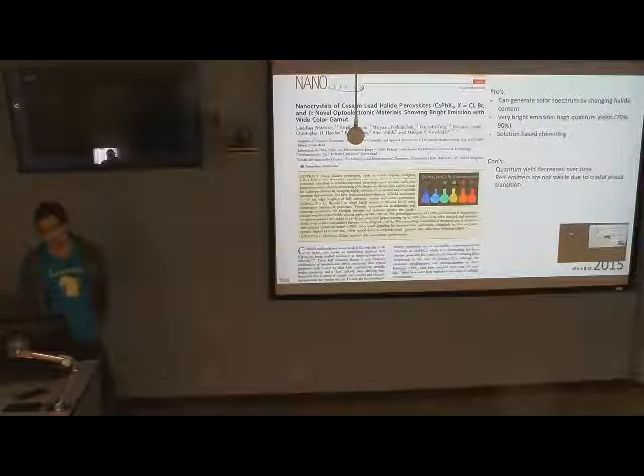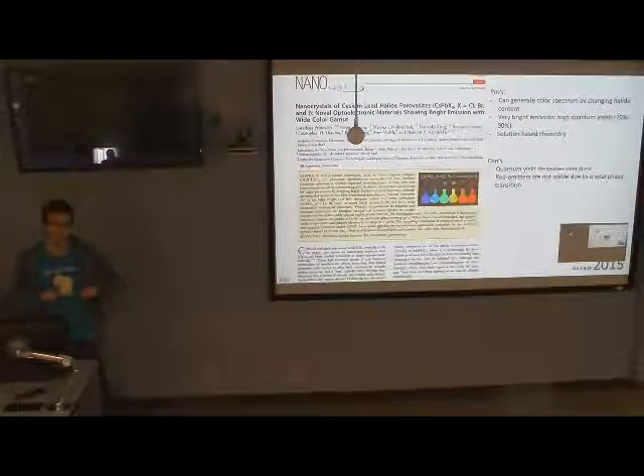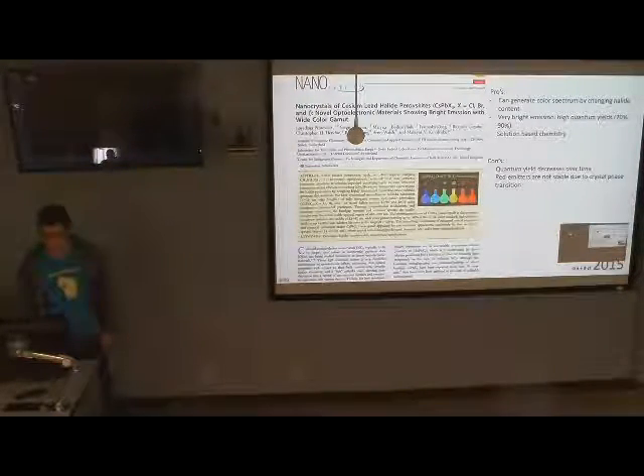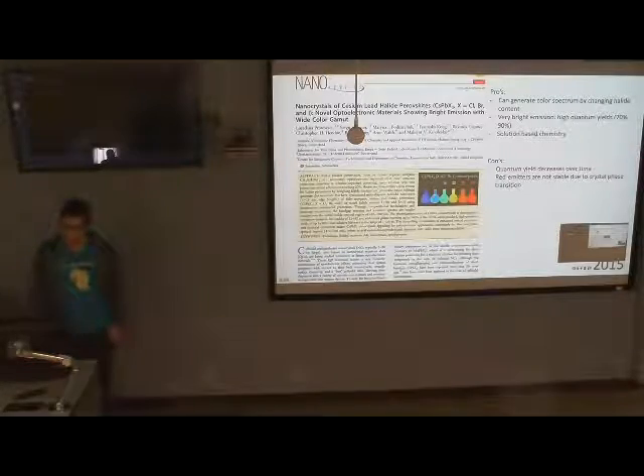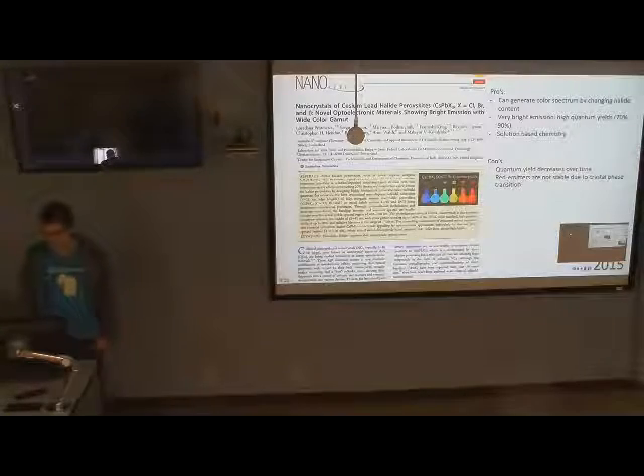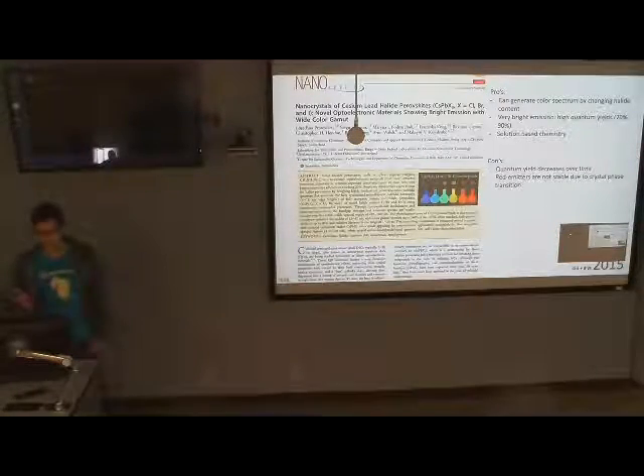They're very bright. When they initially made them, you could get 70 to 90% quantum yields out of them, and people have improved those to basically perfect, or 100%, quantum yields. And they're easy to make. You just mix chemicals together, heat them up, and the reaction goes in like 2 seconds. You can do it pretty much in open atmosphere. But the cons they found are that quantum yields decrease over time, and the red emitters aren't stable due to phase transition issues, but I won't really focus on that. I highlighted the red parts because we're a photophysics group, so the quantum yield decrease over time is something interesting that we can look at.